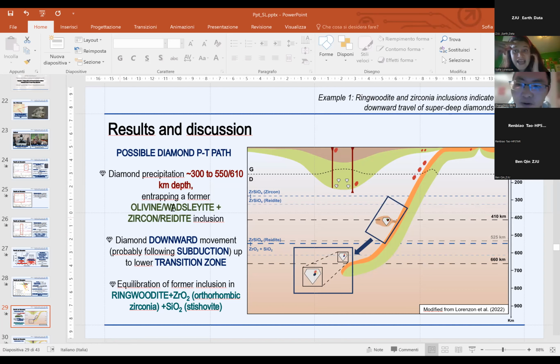But as I said here, considering that super deep diamonds can form from about 300 kilometers depth to at least 800 kilometers depth, we cannot know the exact depth at which this diamond formed. But considering that we think it is probably a super deep diamond, we also say that our multi-phase inclusion is the product of a prograde transformation occurring within the diamond. We suggest a possible depth range of formation.